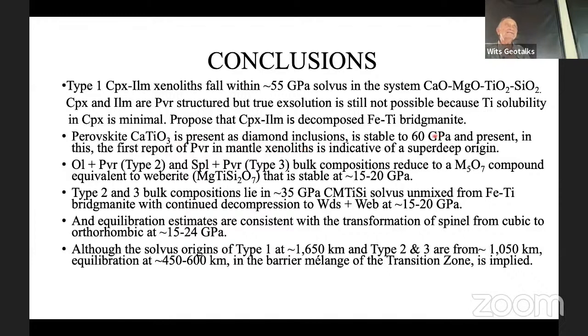Perovskite itself is stable up to 60 GPa and is present in this, the first report of perovskite in mantle xenoliths, and is indicative, in my view, of super deep origin. The olivine plus perovskite, the type 2, and spinel plus perovskite, type 3 bulk composition, reduced to the M3O7 ratio compound, which is equivalent to weberite, that is stable between 15 and 20 GPa.